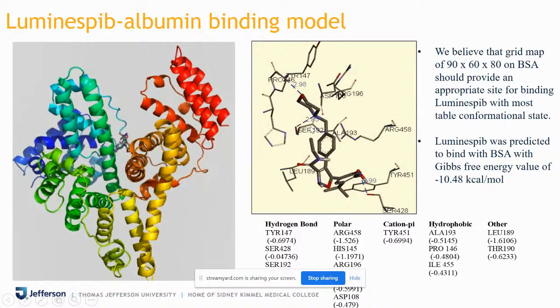The interacting residues of each amino acid in this binding model are shown in the two-dimensional structure over here. In the bottom there is a table with the hydrogen bond interactions, polar interactions, cation-pi, and hydrophobic interactions that are happening between this luminespib and the albumin, shown along with the respective Gibbs free energy. So you see, this is the stable conformation. This is how you can visualize the drug interacting with the albumin, and then when you cause precipitation or complete folding of this protein, it would form a nanoparticle.